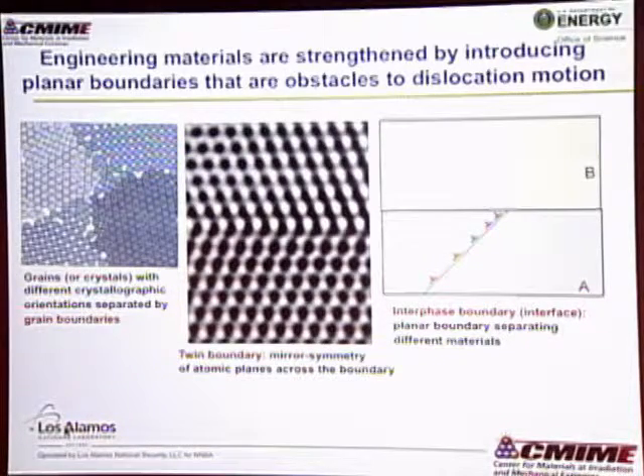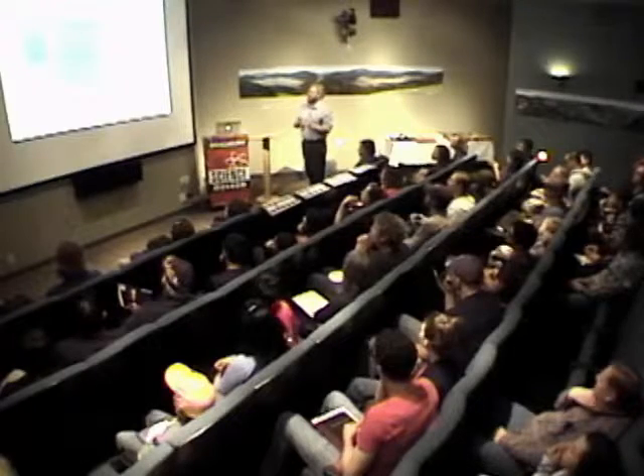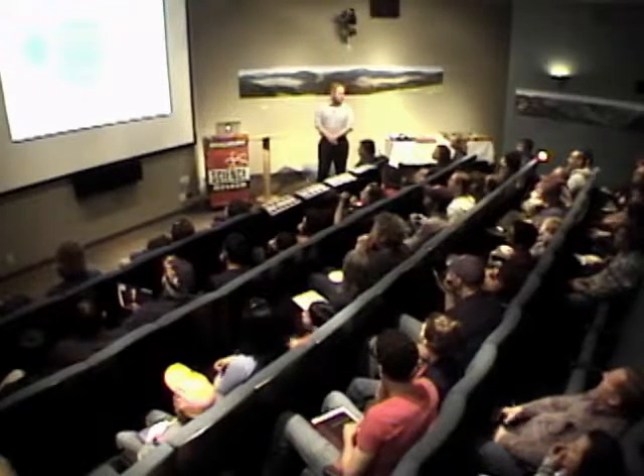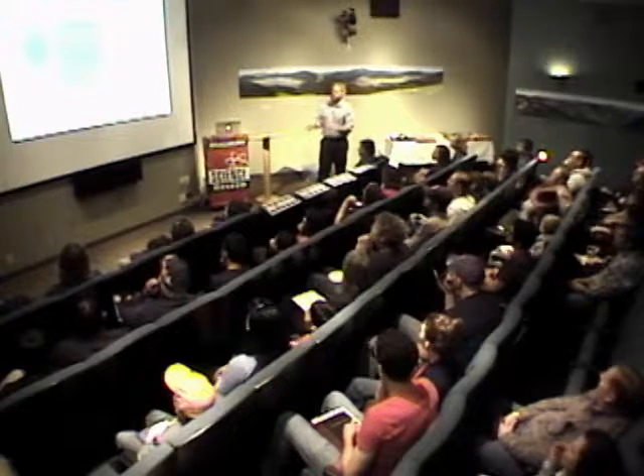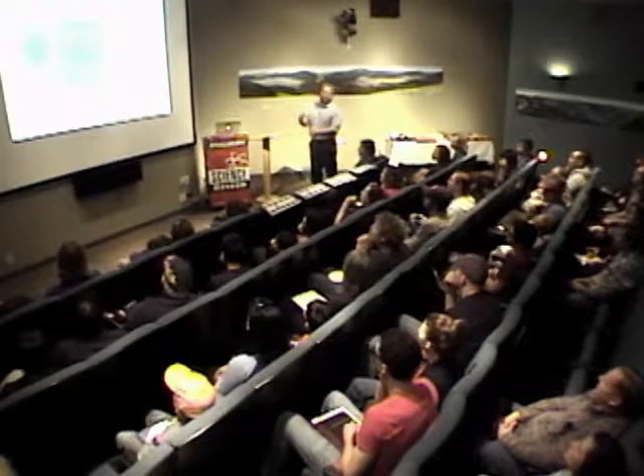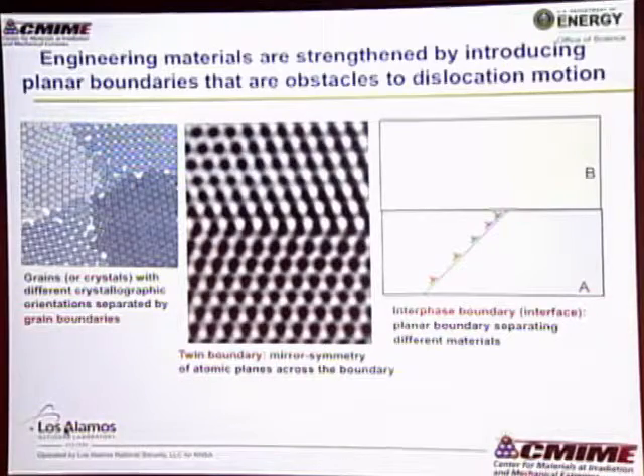So when we talk about real materials, in terms of making a material stronger, one way that we can do it is take these defects that are known as dislocations and make their lives miserable. So what we can do is put in obstacles. Obstacles such as grain boundaries. Real materials are made out of grains, just like grains of sand in a lot of cases, metals that are used for structural applications. You can also put in a boundary, like a twin boundary here. So in this case, you've got mirror symmetry across this twin boundary. If a dislocation has to come in this way, it has to change directions and move this way. It's like a speed bump for a dislocation.